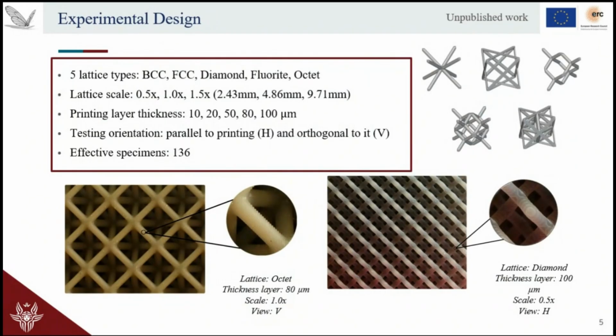In this study, we have considered truss-like lattice structure, and we have considered 5 main cell types: the body center cubic, the face center cubic, the diamond, the fluorite, and the octet structure. In the future, that will be extended, but for now, we have considered only those cells. The cell size has been varied into those 3 intervals, so 2.43 millimeters, 4.86 and 9.71. And we have varied the printing layer thickness from 10 microns up to 100, so covering the whole range of our SLA printer.